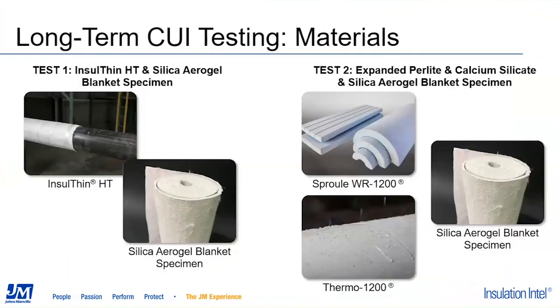Now let's take a look at the longer-term testing that Scott discussed a little bit ago. So this test was developed by leading industry experts, and what it is meant to do is be a longer-term test in duration. So this is a 6-month test. But what we're trying to do is basically take a pipe to failure in 6 months and then analyze the results. So we're trying to boil down what a pipe would see roughly in its lifetime, 20 to 30 years, in a 6-month period. This test has been run twice, and the first test was run with the Insulthin HT product and silica aerogel. The second test was run with the perlite, the Sproule WR-1200, the calcium silicate, and the silica aerogel blanket.